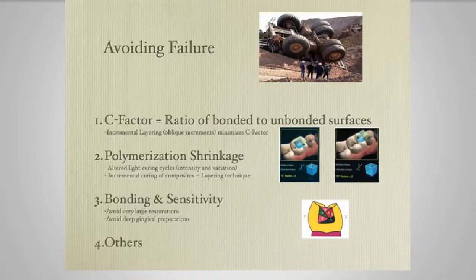Now, polymerization shrinkage is basically the problem also, and one of the ways we can combat that is altered light curing cycles. There are different ideas on this. The best way that's been shown is by doing a ramp technique, basically starting out at 230 milliwatts per centimeter squared. One of the newer studies is showing that if you do that first for 10 seconds, and then turn the light off for at least 10 seconds, and then go back in and light cure again at 450 milliwatts per centimeter squared at the very end, that tends to give you the best way to combat this polymerization shrinkage. Also, incremental curing, a composite and layering technique helps with polymerization shrinkage.